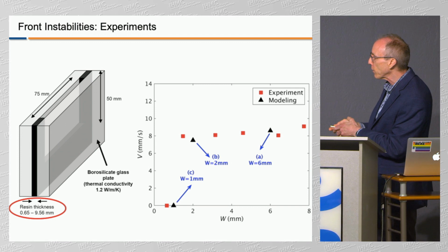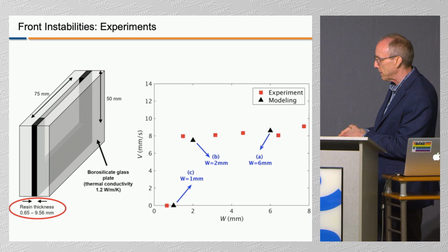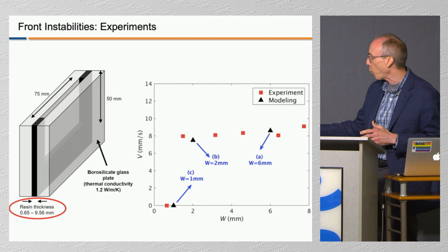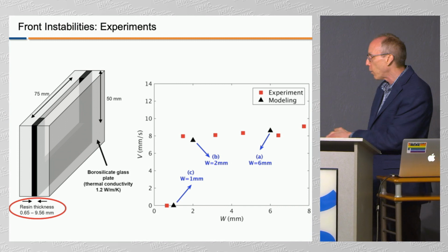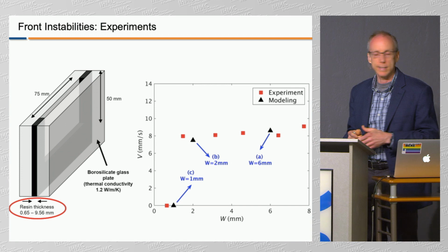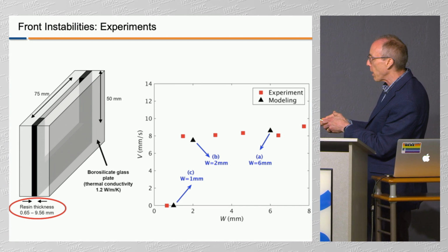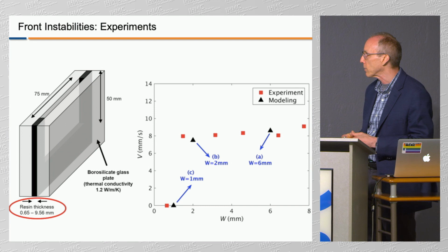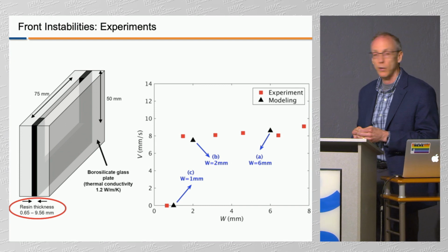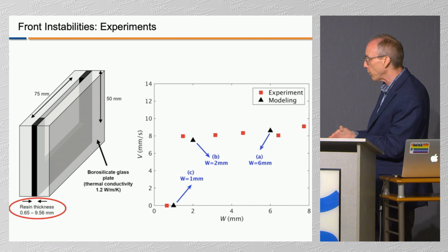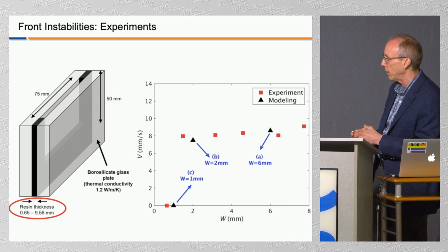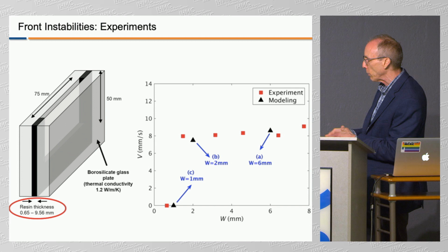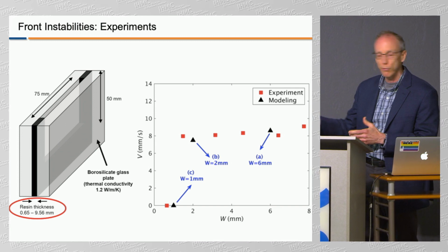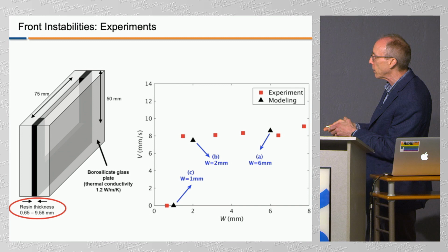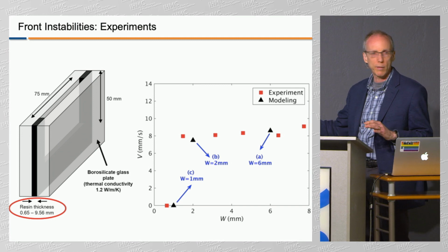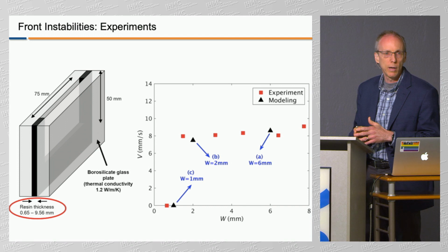And so the frontal velocity, which is plotted on this axis, is 0, because all the heat, so if the width, W, is too small, way over here, it basically just dies out. The experiment is the red box, and the modeled behavior, which I'll show you on the next slide, is the triangle. And so we were getting good agreement between experiment and model. If you're down at 1 millimeter thick or so, we can't propagate the front. But if you get up to 6 millimeters, no problem, the front is very stable, and the velocity doesn't hardly depend anymore on the thickness.